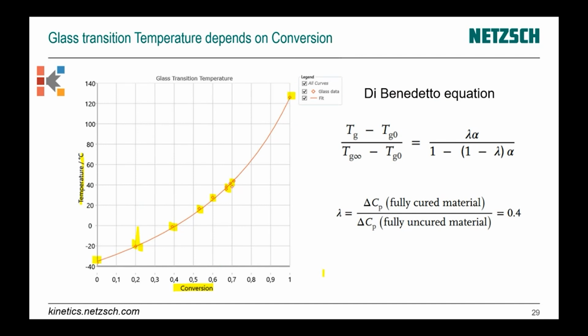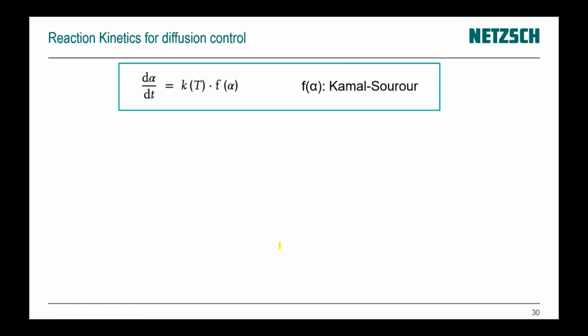We can just fit this data with the Di Benedetto equation inside our software. And then we have the parameters of the Di Benedetto equation, and we will use this equation inside the software in order to find what is the current glass transition temperature for the current degree of cure during the whole curing process. And if we are above it, then the reaction goes fast. If we are below, then the reaction goes slow.